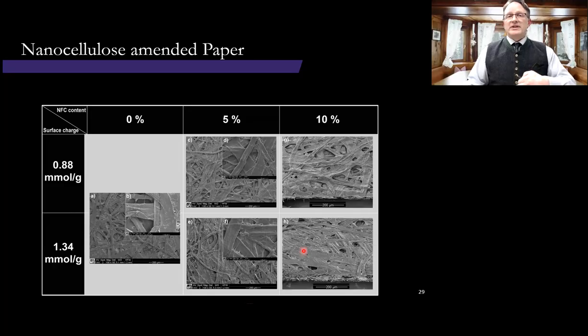What happened when we doubled the high charge amendment, we got the opposite. And you can see this when we were actually forming the sheets. You can see that the electrostatic repulsion was starting to dominate the formation. There were large flocs forming. And if you look at the edge here, you can see that the bulk of the sheet actually increased and got larger.